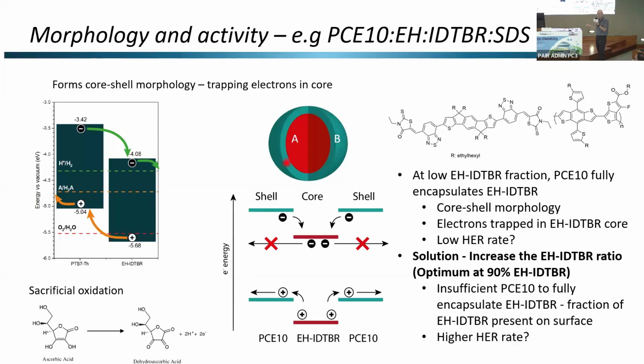But the problem that we can see with this core-shell approach is, okay, once we transfer our holes to the shell, that's all very well. It's very nice. We've got our potential for oxidation at the surface. But the worry here is that the electrons that we have on our EHIDTBR, they're buried in the center of the core of the nanoparticle. So that's not really a very efficient setup for the reduction reaction that occurs with the platinum on the surface of a nanoparticle. So this was a worry.